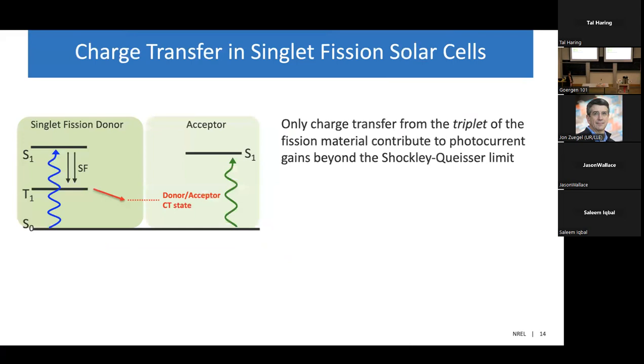So going back to the singlet fission solar cell, here I have a simplified schematic for the device. We have a material that's able to undergo singlet fission to produce these low energy triplets. And then again, we want our donor acceptor CT state to lie somewhere below the triplet level of that fission material in order to actually extract those excitons as free charge. So this schematic is good, but if we have a donor acceptor CT state that's somewhere up here, we're not actually able to take advantage of the fission process.